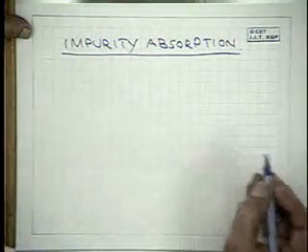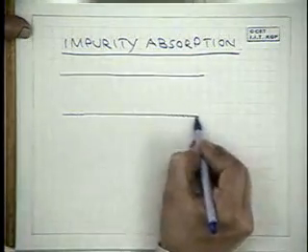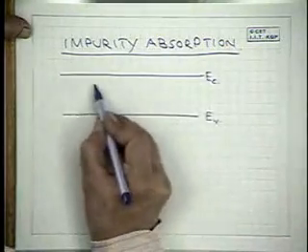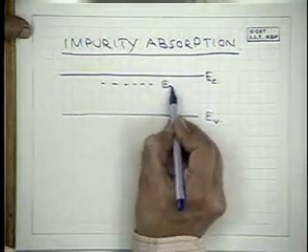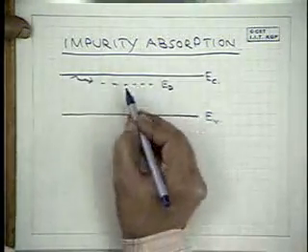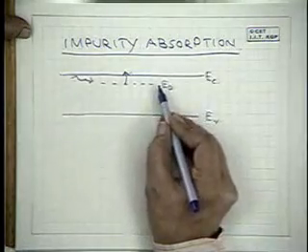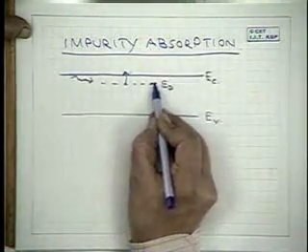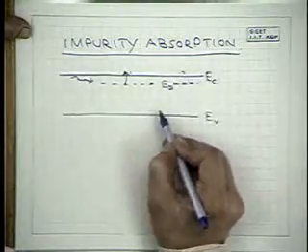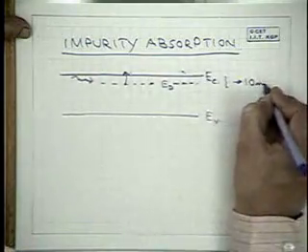Impurity absorption can be of different types. One can have radiation coming and exciting electrons from donors into the conduction band. This is important at low temperatures because the donors must have electrons. They must not be ionized. The donors must have electrons which are excited into unfilled states. Obviously, this energy is of the order of say 10 meV or so, long wavelength.